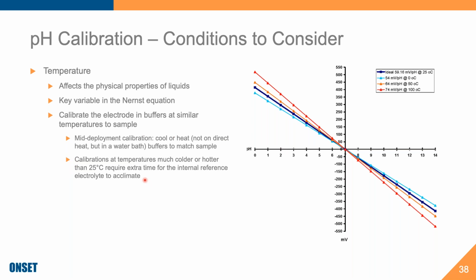Calibrations at temperatures that are a lot colder or hotter than 25 degrees C will require extra time. So keep in mind that within the tolerances of your manufacturer's electrode, it is okay to calibrate at different temperatures. Just make sure that you're remembering that your pH electrode that was sitting in your car, for instance, on a hot day in Florida, is likely going to have an internal temperature of that electrolyte that's somewhere in, let's say peak summer, the 90s even, but your water's like 70 degrees. So you'll want to make sure that you give your electrode time to equilibrate to the sample, or that you're also calibrating to the sample's temperature and also letting the electrode equilibrate to the buffer.